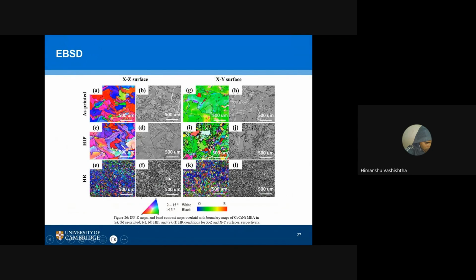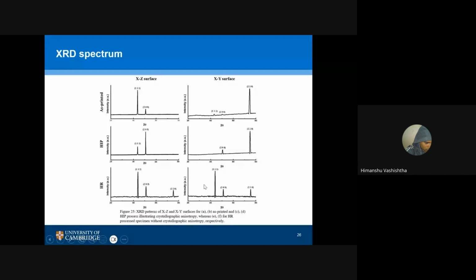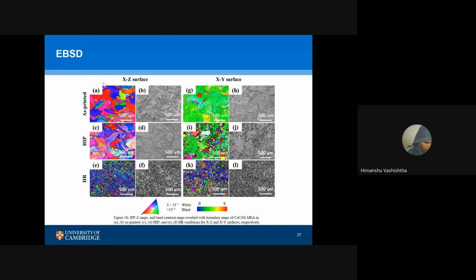So when you rolled it, you can see a lot of grain refinement was there, and this heterogeneity is gone - the same thing we saw in the XRD. Either it's XZ surface or XY, there is no heterogeneity. Here the heterogeneity existed till the hot isostatic pressing process. So that's the as-printed thing, that's the hot isostatic pressing thing - you can see the heterogeneity is there. The highest heterogeneity is in the as-printed case, here it's a little lower, and here it's almost gone.